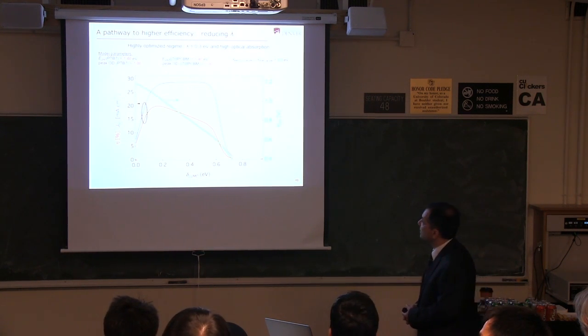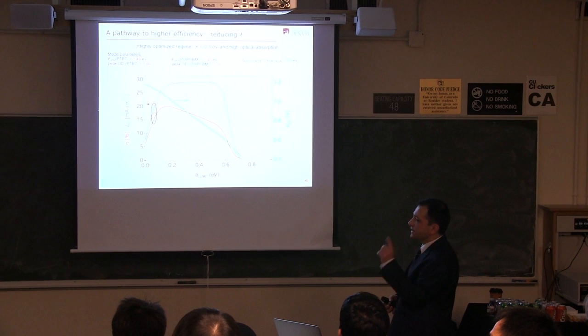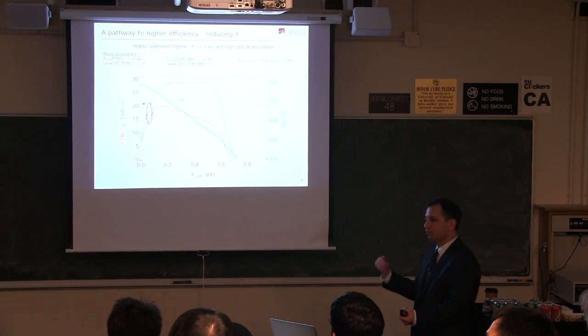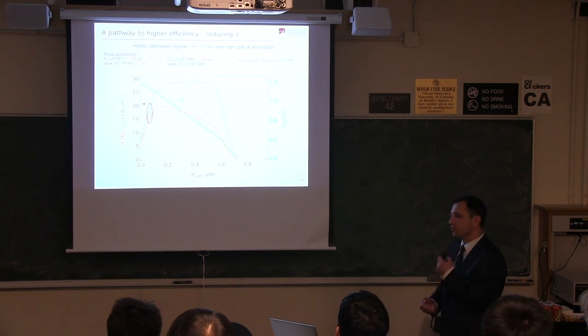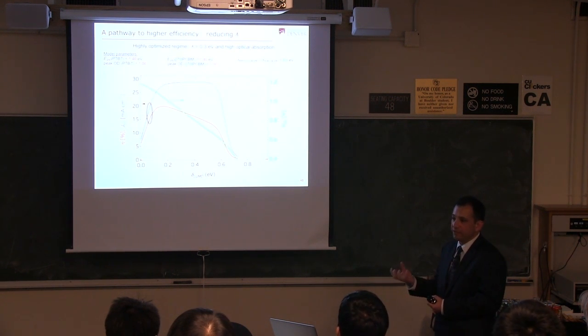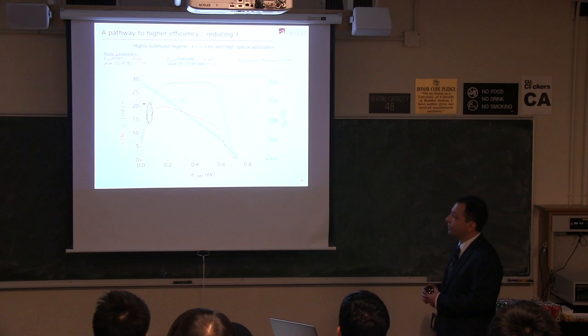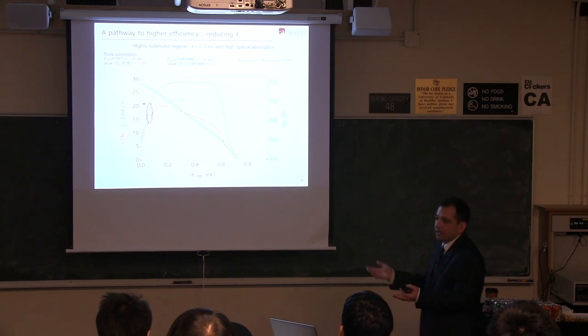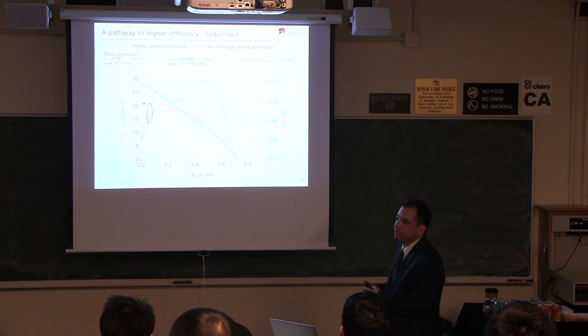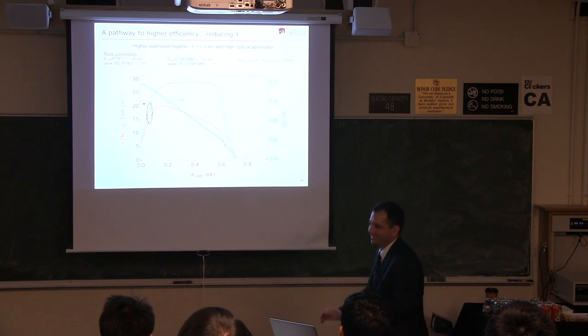Does that change your energetics? It does, because now the reorganization energy is fully on the organic material, and there would be essentially 0 in the acceptor. It's not that much different because I didn't tell you, but of the two materials, the polymer and the fullerene, this lambda is almost all in the polymer. Fullerene is a very structurally sound material. So the reorganization energy there is, I don't know, 20 meV, something like that. So 20 meV, yeah, very small.